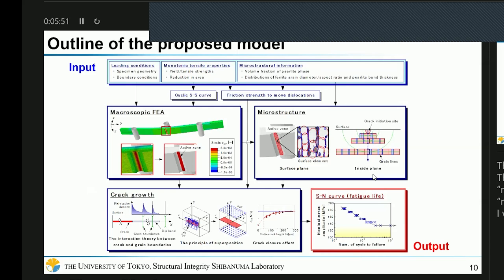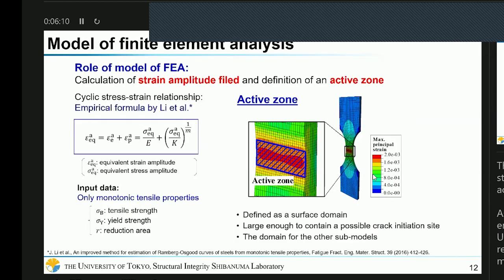This model is composed of three sub-models: macroscopic finite element analysis, the microstructure model, and crack growth. I will show you the outline of these respective sub-models. The first one is macroscopic finite element analysis. The role of this macroscopic finite element analysis is the calculation of the strain amplitude field and definition of an active zone. As a cyclic stress-strain relationship, we employ the empirical formula by Li et al. And using this formula, we can estimate the cyclic stress-strain relationship based on only monotonic tensile properties. And then we define the active zone as a surface domain based on the strain distribution. And this active zone is an evaluation domain for the other sub-models.